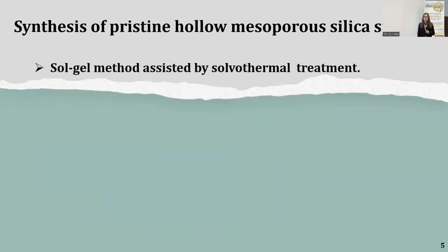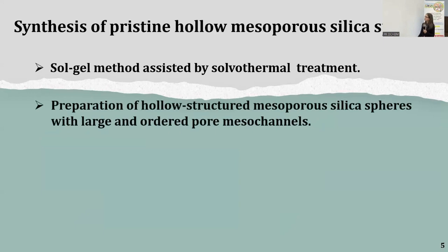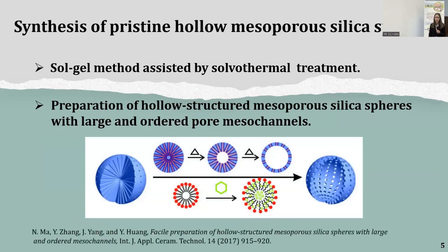Pristine mesoporous silica spheres were synthesized by sol gel method using tetraethyl orthosilicate and hexadecyl trimethyl ammonium bromide as silica source and structure directing agent respectively. Then a solvothermal treatment was applied to obtain hollow structure mesoporous silica spheres with large and ordered pore mesochannels. In this image, you can see the solvothermal treatment.